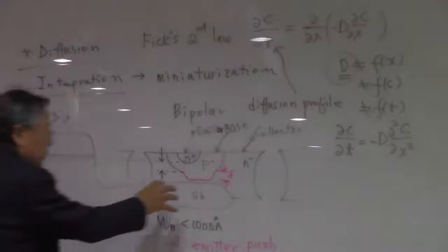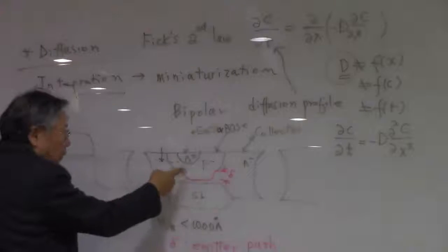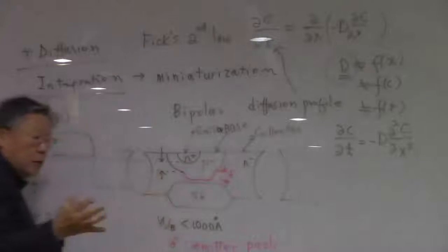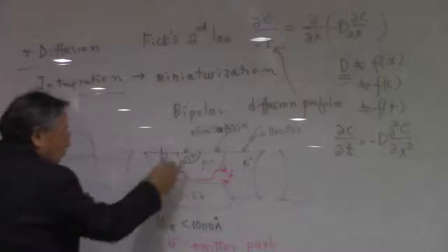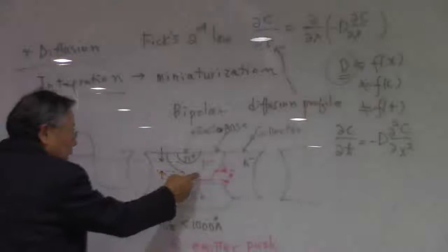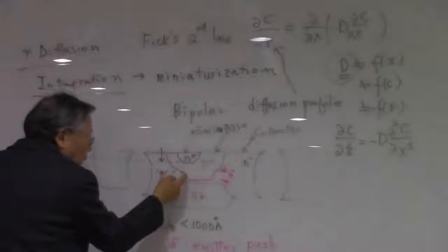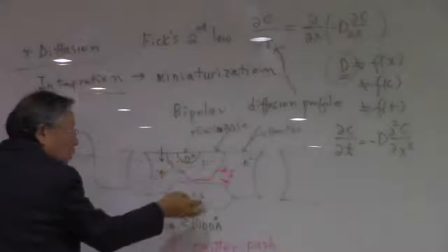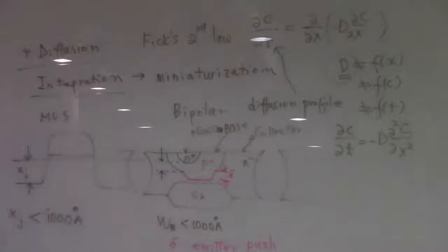And that thing happens because of this environment. If you have boron and then on top you diffuse your phosphorus, for example, for the emitter, then this phosphorus creates a lot of vacancies inside the boron doped region, so that the region which is just beneath the N plus is going to have an extra diffusion of the boron.